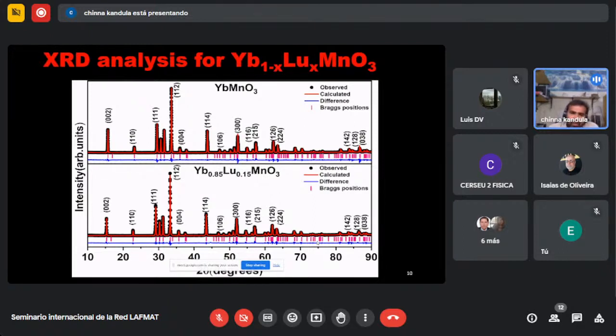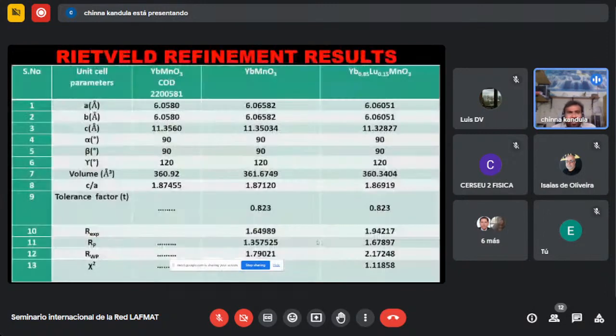After that, lutetium is doped at 15% on the Yb site. The same thing happens, but the exact peak positions may shift because of the dopant. In order to know how much the lattice parameters of the unit cell change, we do Rietveld refinement. In the next slides I will show the Rietveld refinement results. This is the parent compound. I took the database from the Crystallography Open Database. This is my parent compound. What about the one prepared with 15%?